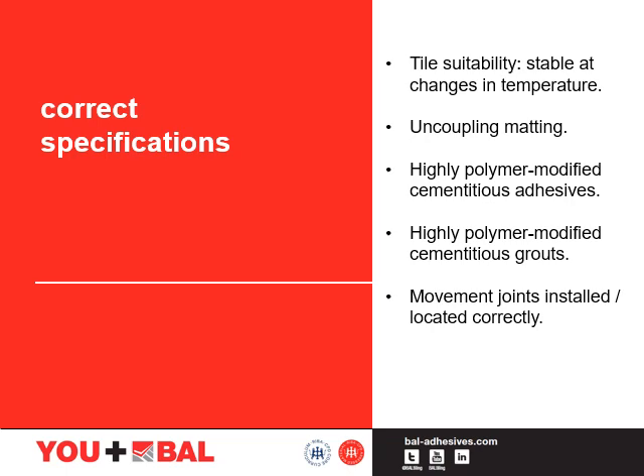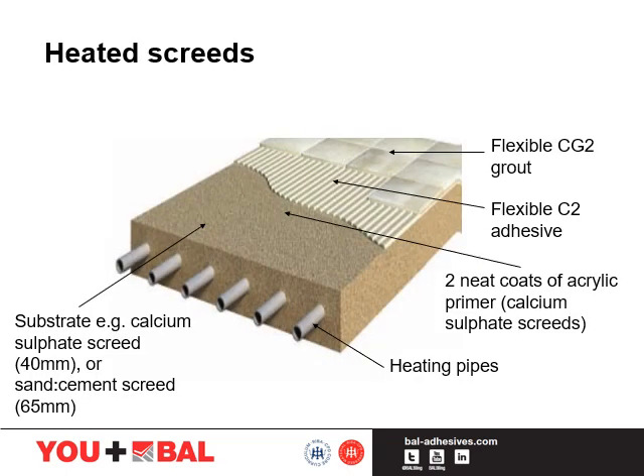We need to use highly polymer modified cementitious grouts and adhesives. And also, when tiling with natural stone, we need to make sure we're using the right colour, so a rapid setting white product must be used. Movement joints must be used and installed correctly, in line with BS 5385 Part 3. Specifying suitable and trusted adhesives and grouts certainly helps accommodate the thermal movement.